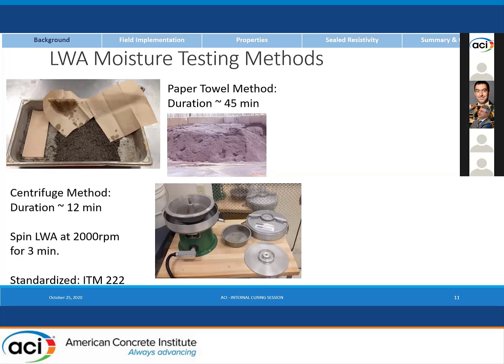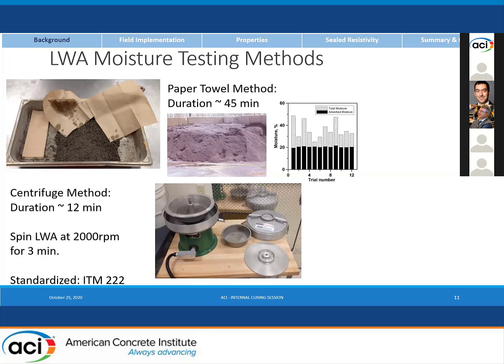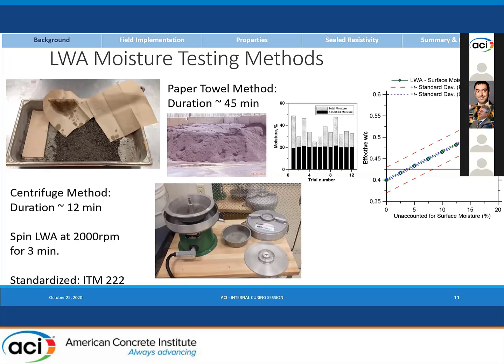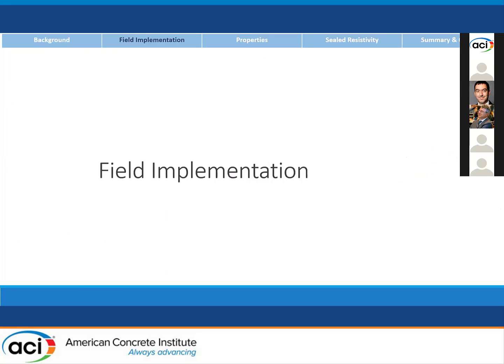All you do is you spin the lightweight aggregates for 3 minutes at 2,000 RPM. And it turns out that indeed it is a very robust method that you can consistently recover the correct value for the absorbed moisture and the surface moisture. The other side of it is the uncertainty in the paper towel method. Actually, if you run the test and you make the correction, the uncertainty is so high that you could still, in theory, be out of specification for a water to cement ratio. And so the centrifuge method does eliminate that issue.